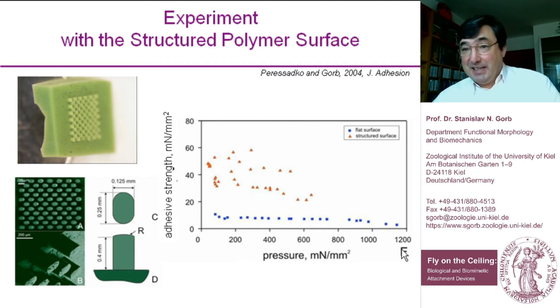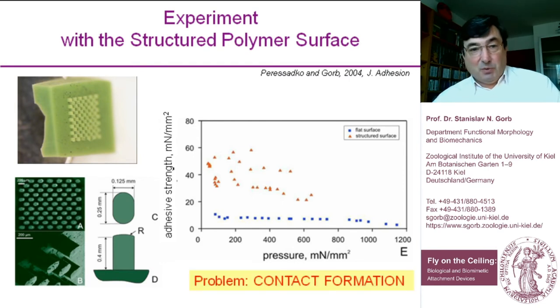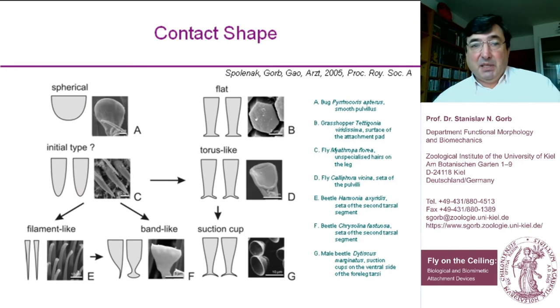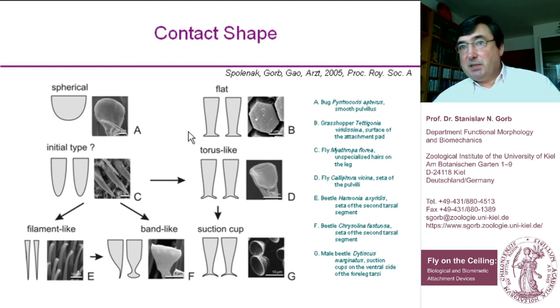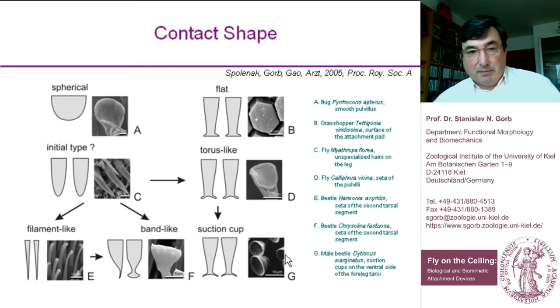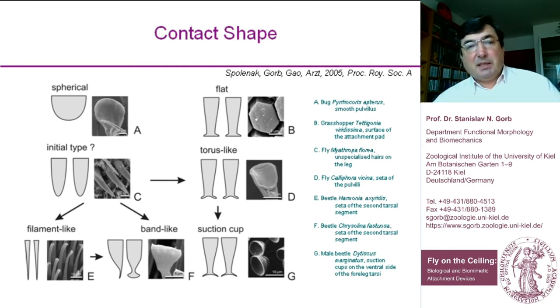The explanation for fast contact formation has something to do with the contact shape of the structures. There are some spherical contact elements, some flat torus-like shapes, and even some suction cups — quite rare, with some of the smallest suction cups in the world at 10 to 15 microns. Interestingly, most animals that can walk on the ceiling have this kind of blade-like or spatula-like structure, which is quite unexpected and unusual.